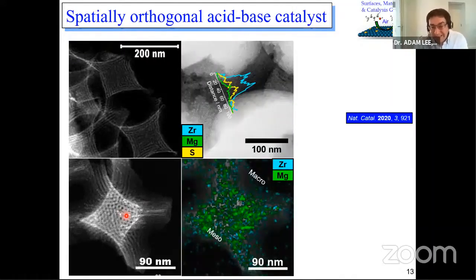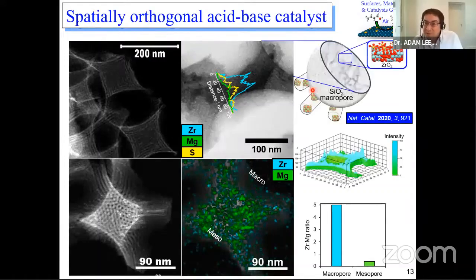So if you now do some careful EDAX mapping, so we're now looking at elemental analysis, what you find is that nearly all the magnesium sits inside the mesopores, these small channels, and most of the zirconia is on the outside. It's coating the macropores. So this is a kind of image that we have here. We have a macropore. Now instead of a metal catalyst inside it, we have a thin coating of zirconia. And in the smaller pores, we have magnesium oxide nanoparticles. And it's easy to see by looking at the ratio of our zirconia to magnesium. What you find is that in the macropore regions, there's a very large amount of zirconia, whereas in the mesopores, there's basically no zirconia, only MgO. So again, we've achieved spatial separation of these two active catalysts, sulfated zirconia and magnesium oxide.